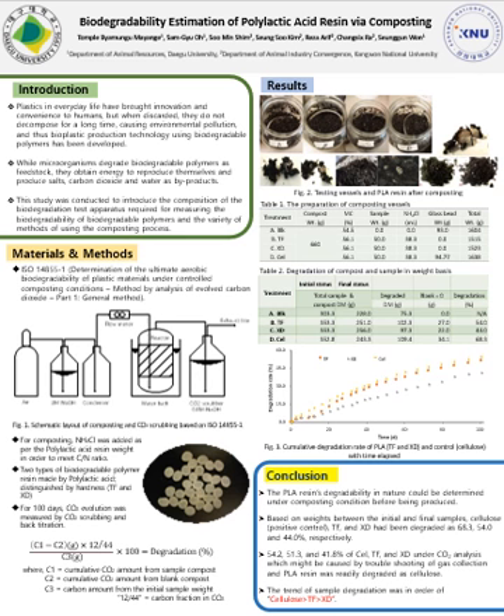So to conclude, the polylactic acid resin's degradability in nature could be determined under composting conditions before being produced. Then, based on weights between the initial and the final sample, cellulose, which was the positive control, followed by TF and XD, had been degraded at 68.3, 54, and 44 percent, and then 54.2, 51.3, and 41.8 percent for cellulose, TF, and XD under CO2 analysis, which might be caused by troubleshooting of gas collection also. And the polylactic acid resin was readily degraded like cellulose.